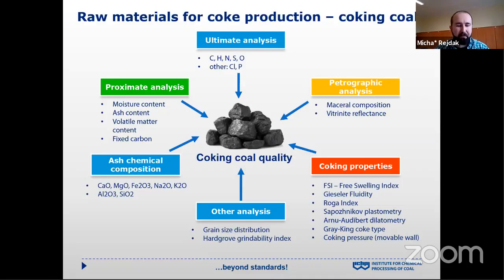It's a very useful parameter which can help assess the safety of the coking process in terms of the coke oven battery, because there are some coals which can generate excessive pressure and which can damage the oven walls of the coke oven battery. So it's also important to assess the coking pressure of the coking coals.